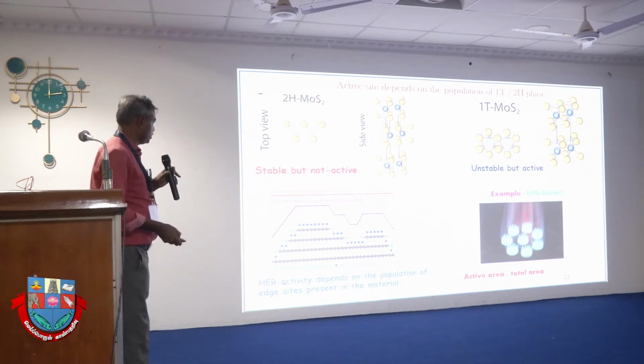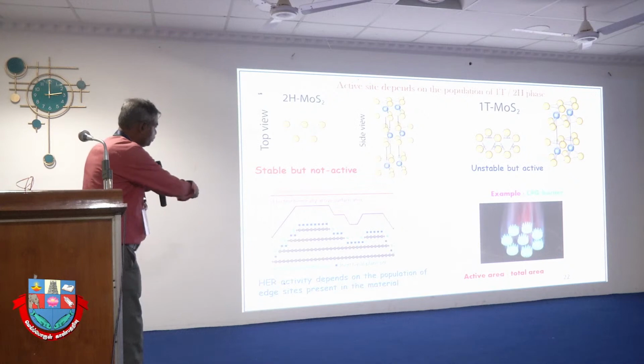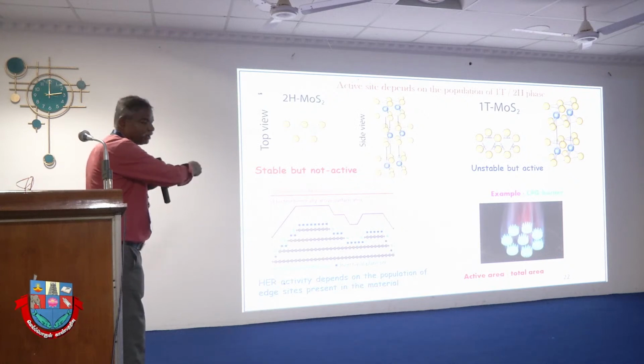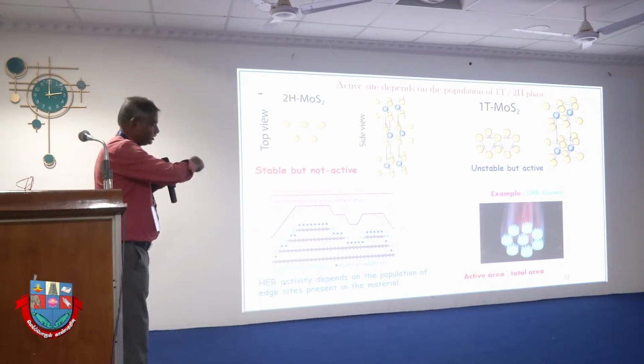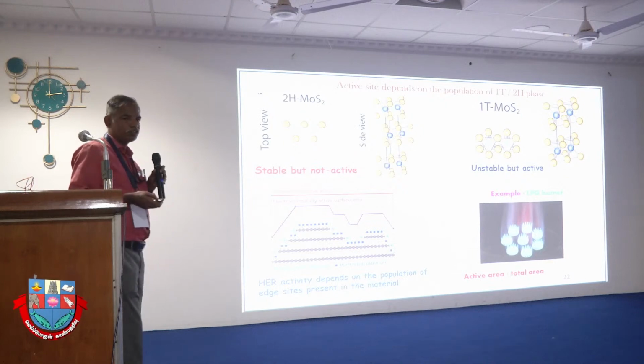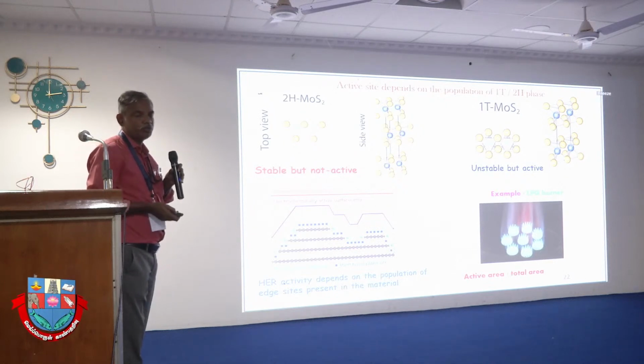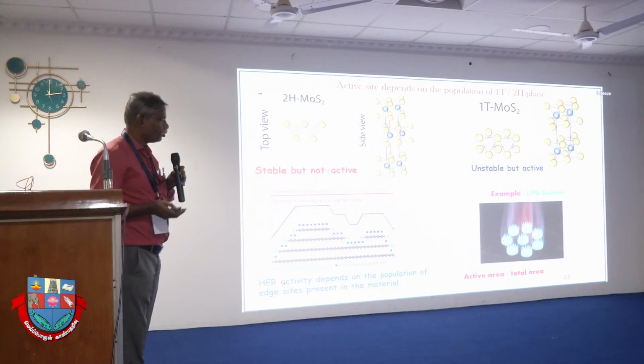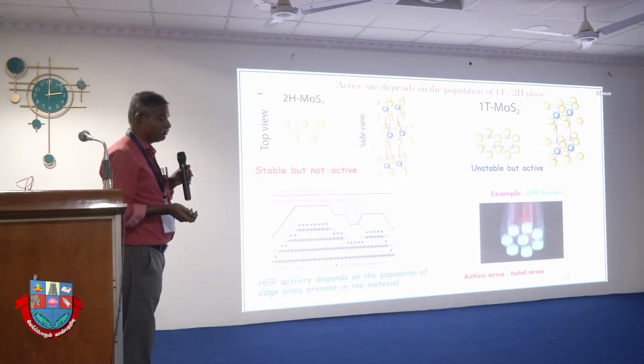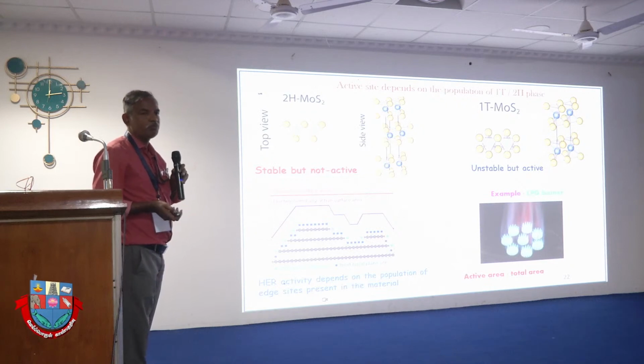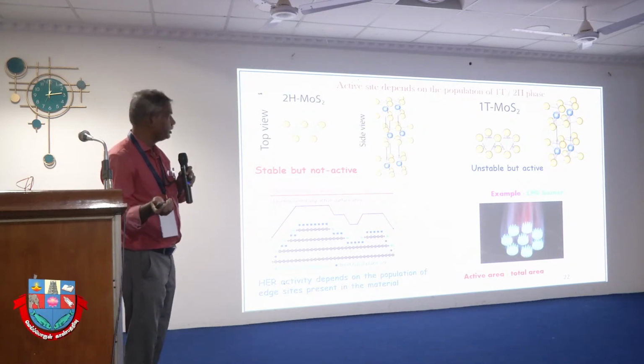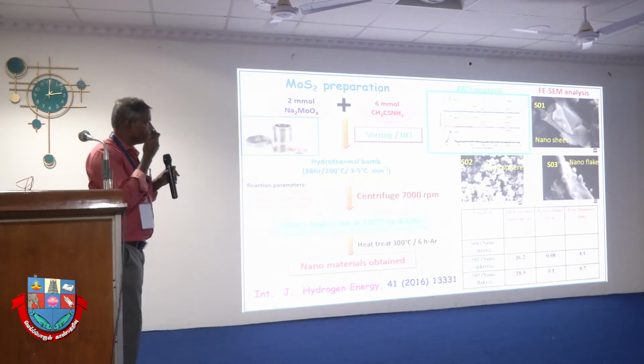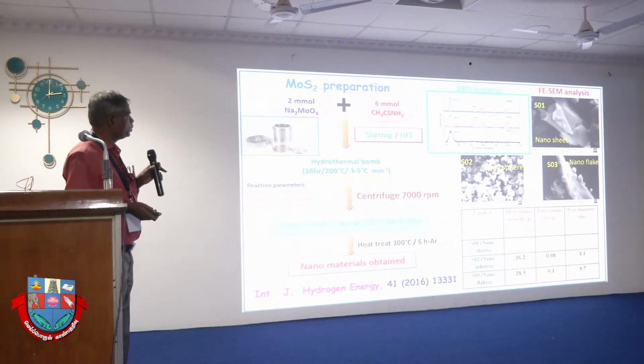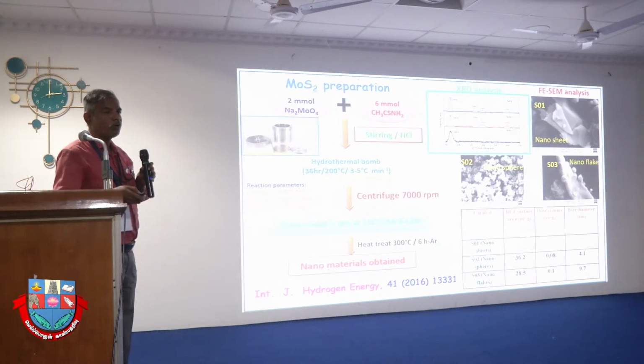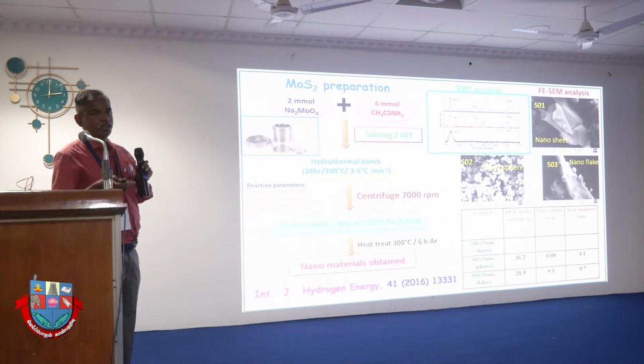The stable form is active only due to the active centers available on the surface, because the entire geometric area will not be useful for hydrogen generation. Only a fraction of the geometric area will be used for HER, so the surface area versus the electrochemical surface area will be totally different, and so the activity will be different. In this case, we prepared MoS2 in 3 different morphologies, because we want to alter the morphology of the material so that we can change the